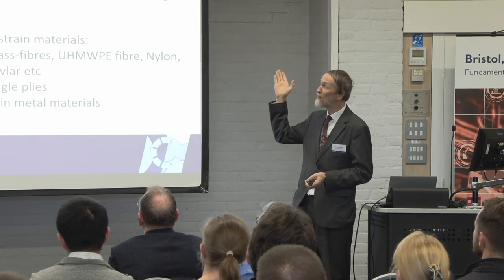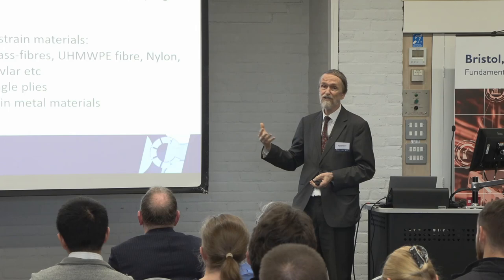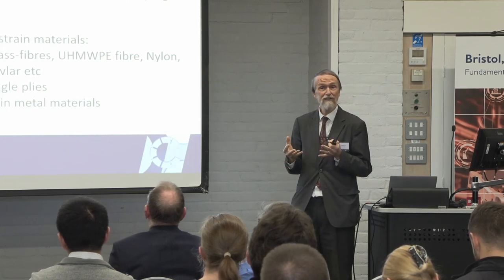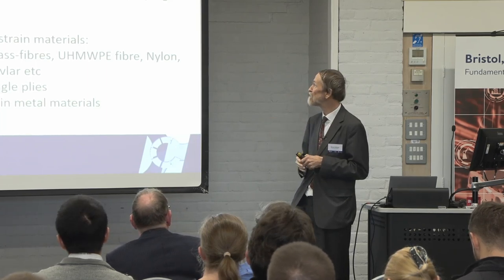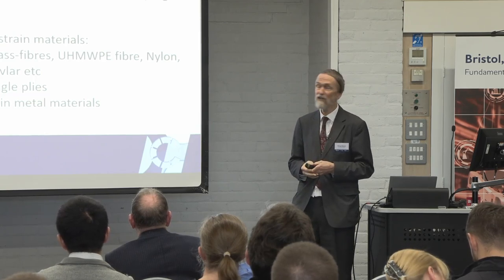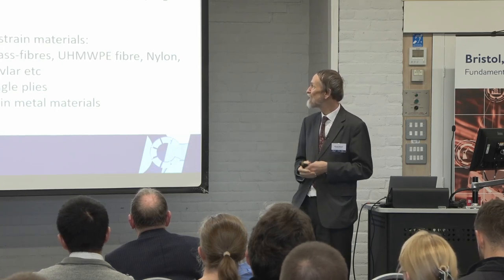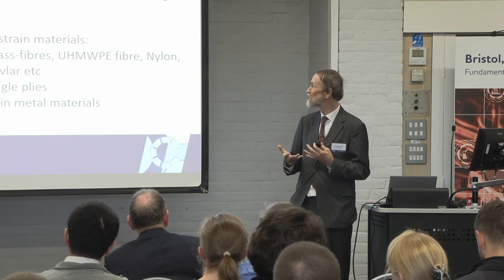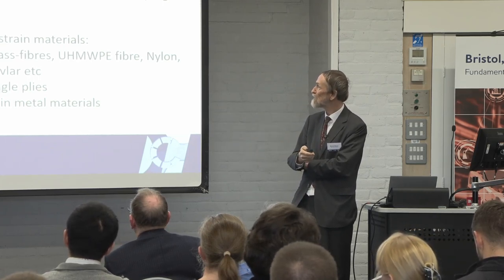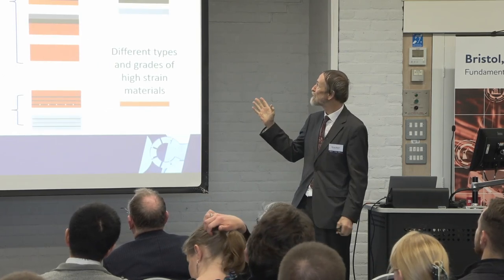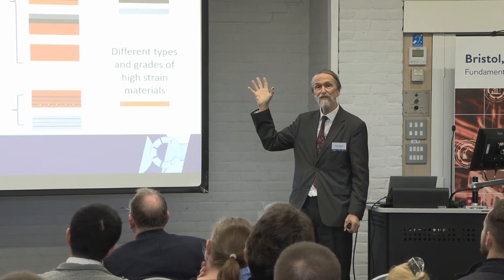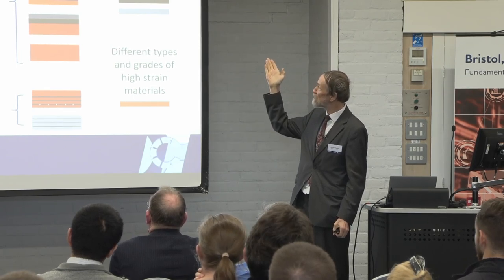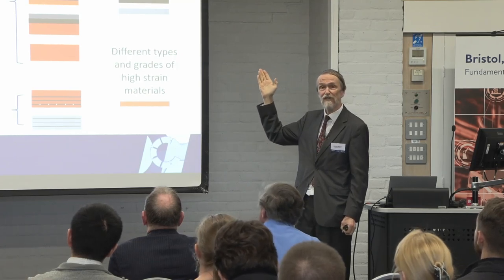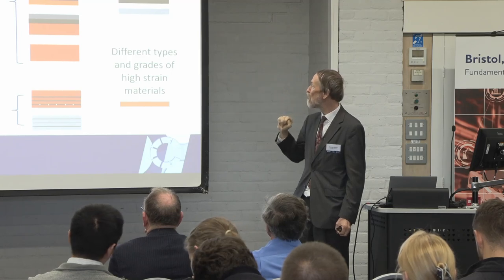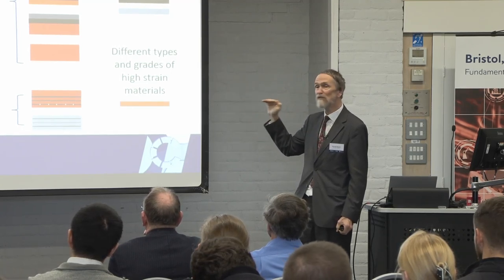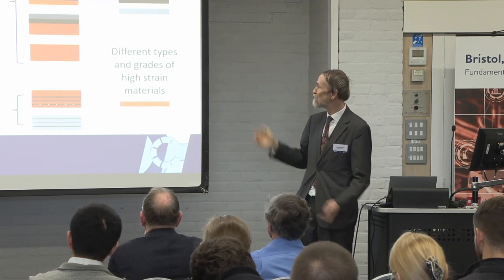And we can combine different types of materials. So in terms of the carbon fibers, there's a range of different types of carbon fiber, high modulus, high strength, intermediate modulus. And we can also be looking at different ply thicknesses, standard prepregs, but also ones with thin plies. And the high strain materials, there's a whole range of different materials which we can use: glass, polyethylene, nylon, aramid. And we can also look at incorporating different orientations of the angles and also potentially metals as well. So what we're going to look at then is combining in different ways, either by blocking the materials together, where I shall show some results comparing carbon with glass and different combinations of carbon and glass hybridized together in a block form, or in a ply-by-ply hybridization where we try to bring different materials together at a lower level to influence the behavior.